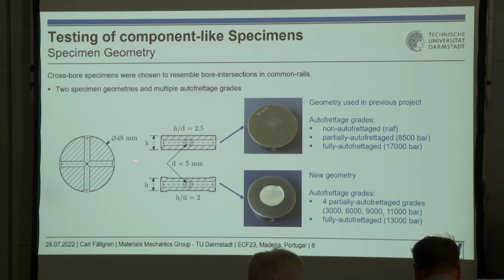So the main difference between the two specimens we chose is the ratio between the height of the specimen and the diameter of the bore. The thicker specimen has a ratio of 2.5. The bores always were the same, and we machined out a part of the original specimen geometry to have a thinner specimen with an H/D ratio of 2. We also had multiple autofrettage grades: 3,000, 6,000, 9,000, 11,000, and also a fully autofrettaged at 13,000 bars. If 3,000 bar really can be called autofrettage is a question I cannot answer, but it also induces some kind of residual stresses.